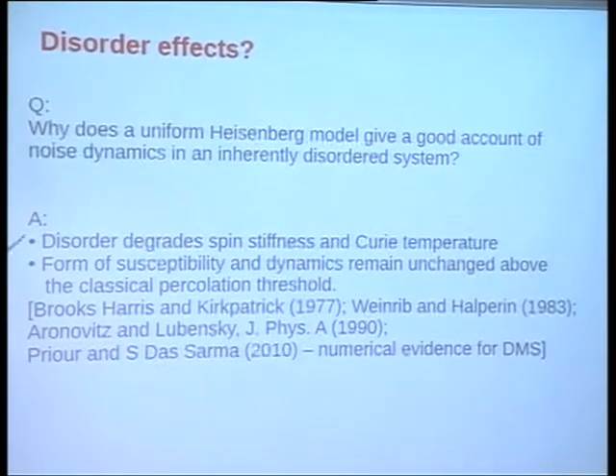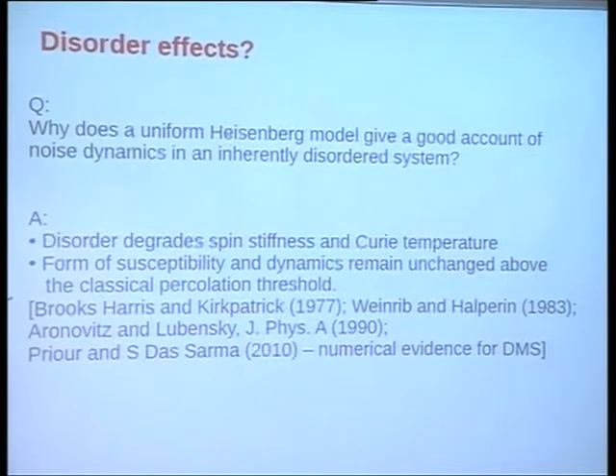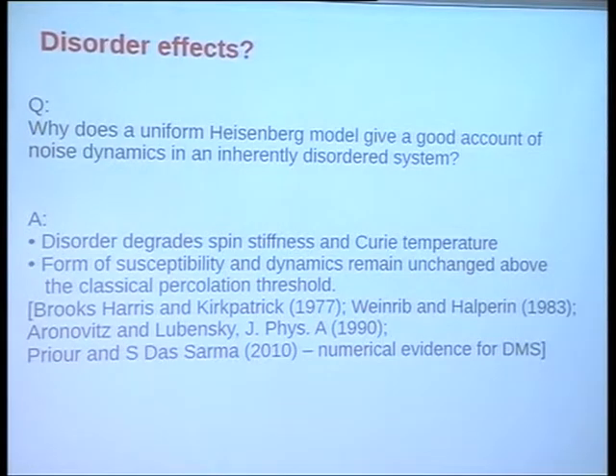So the argument for disorder is that disorder degrades spin stiffness and the Curie temperature, but provided that the disorder is not extreme, which I'll qualify later, the form of the susceptibility and dynamics can remain unchanged until you are above the so-called classical percolation threshold. What I mean by this is, you start taking manganese atoms out randomly in the Heisenberg model, and you ask in the two-dimensional story, under what circumstances I can no longer describe the correlation function as an exponential behavior with some modified TC, and I have to look at a completely disordered story or a completely different universality class.